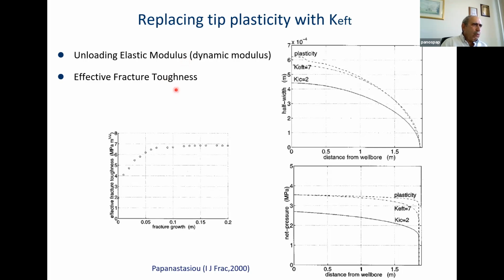To show that, I have one of the diagrams which shows the calculation of the effective fracture toughness with fracture length. I will take the limit value here, and I will use this limit value in the elastic simulator, and then compare the results with the full plasticity model. And this is what we did here in this diagram.